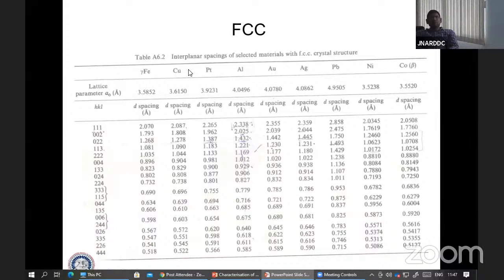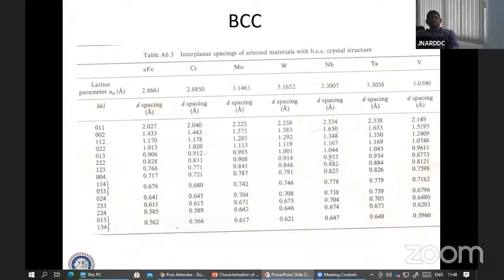Suppose you are doing analysis for iron, so your lattice parameter is, suppose, 3.5, and your d-spacing is, suppose, 2.07, you get a d1. So you can index that as a 111 HKL. Then suppose your d2 is 1.26, then you can index it like a 022. So likewise, you can index your spot pattern by using this data available in the books or in the software. And this is for BCC materials.